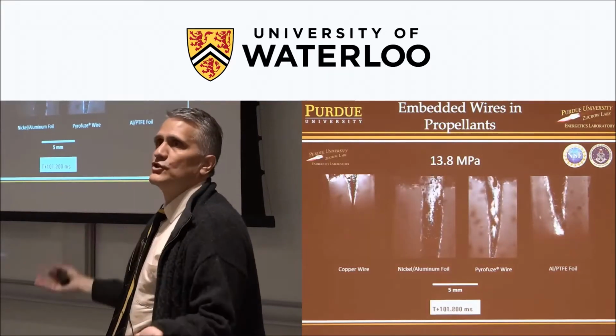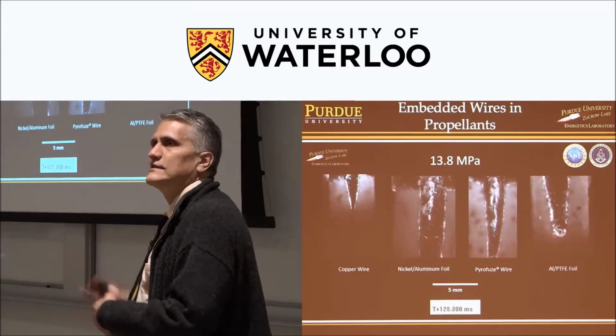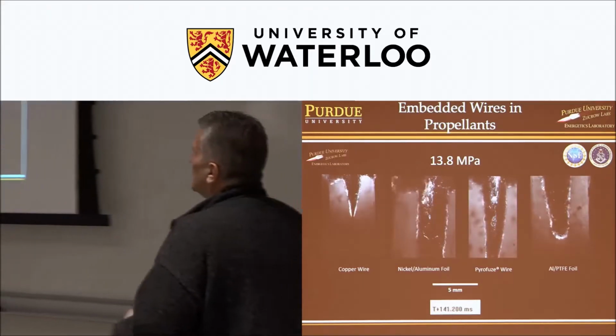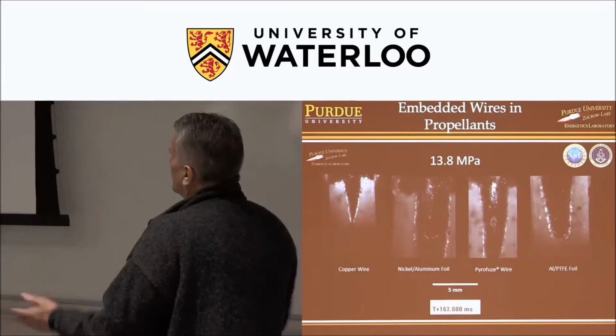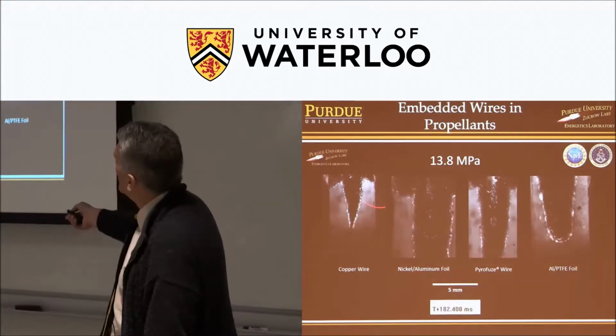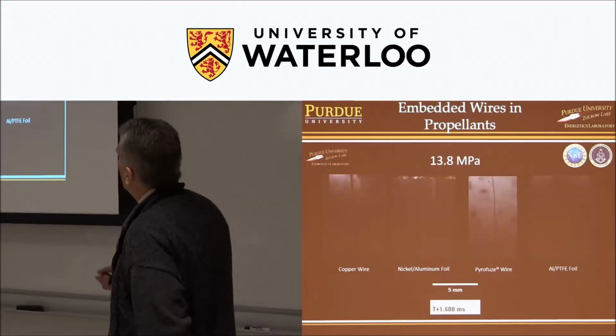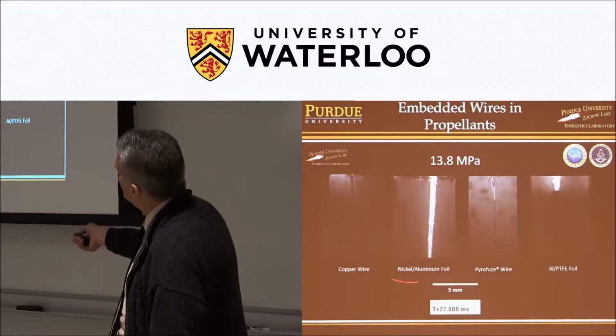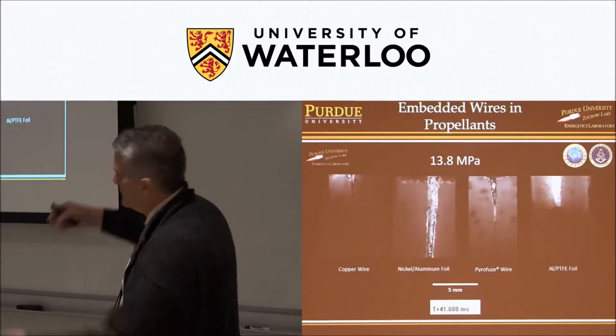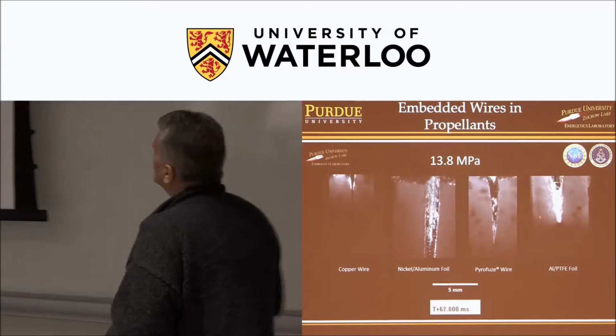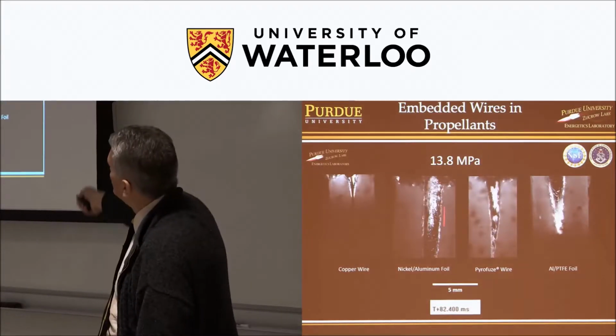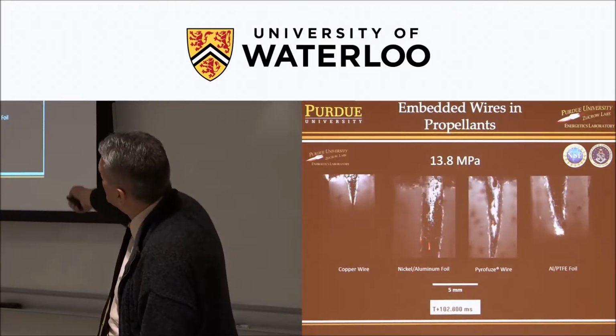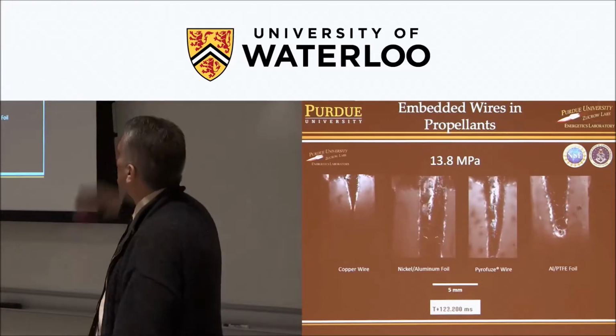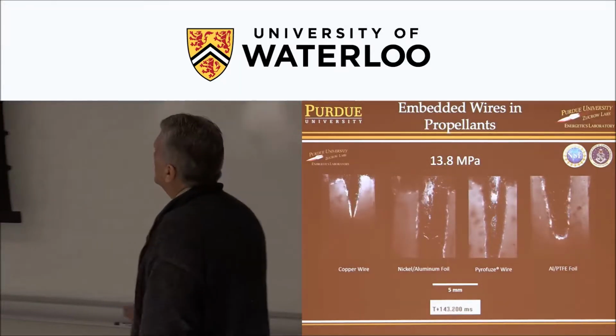That increases the surface area and therefore increases the effective burning rate. So higher surface area that regresses back, that means that you'll have more of that propellant burning up at a faster rate. This is the nickel aluminum foil. It's a nanostructured layered material, and it's going much, much faster. You really have a hard time seeing the V structure. It shoots down through the propellant.